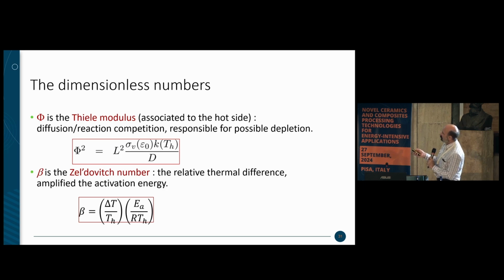One is the Thiele modulus, which takes the length through the thickness dimension here, and then you got the surface area and the hottest chemical rate constant here divided by the diffusion of the gas. So it's the diffusion reaction competition. And if that length is too large, of course, it means that you are depleting completely your reactant inside your preform. And the other one is the Zeldovich number, which is the relative thermal difference amplified by the activation energy.